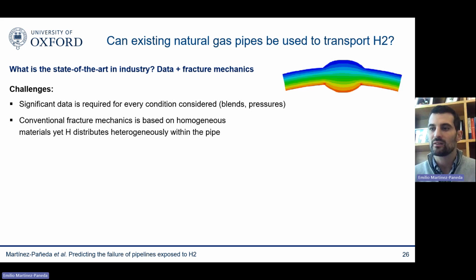Fracture toughness is something that you measure in an homogeneous sample. But the pipes, as you can see here, are not homogeneous. So the idea of a K field, a stress intensity factor, a fracture toughness, those ideas of fracture mechanics work very well if you have an homogeneous sample. But at the moment you have an heterogeneous hydrogen distribution within your pipe, as you can see here, because we go from this region where you're exposing your pipe to hydrogen to this outer region where the hydrogen is free to leave the pipe. The moment you have this kind of heterogeneous distribution, because of the sensitivity of the fracture toughness to the hydrogen content, you have basically an heterogeneous distribution of fracture properties. And then you no longer can apply fracture mechanics. So that's a challenge.